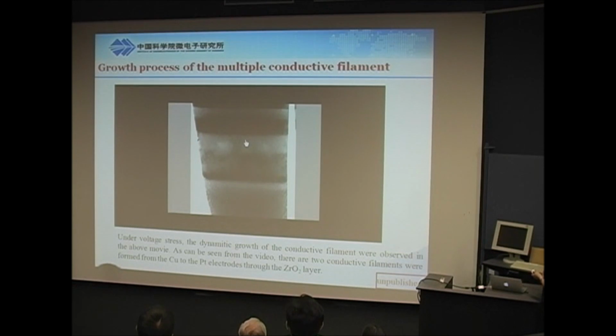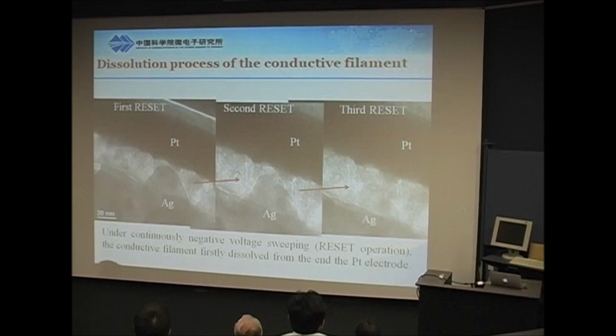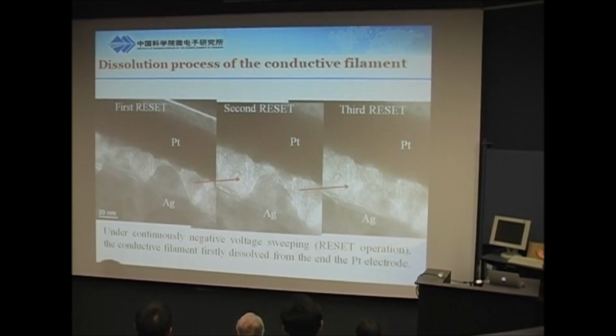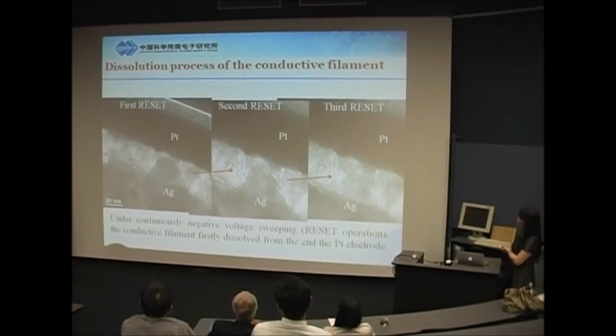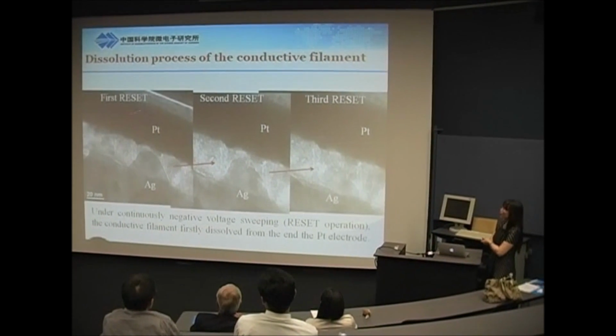So it's a very slow area. Because if it's very fast, it's not easy to capture these pictures. So finally, we can observe the two filaments formed in this observed area. The challenge for this work is how to prepare the sample. This is a big challenge. Also, we captured the reset process.